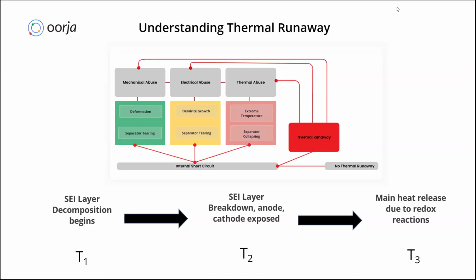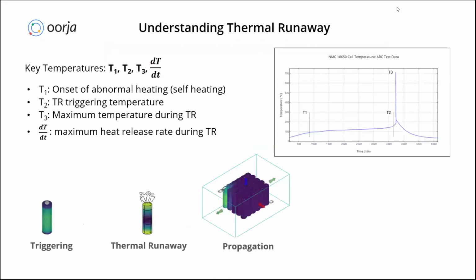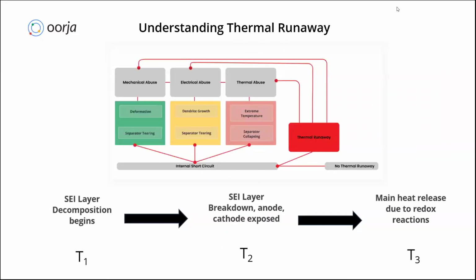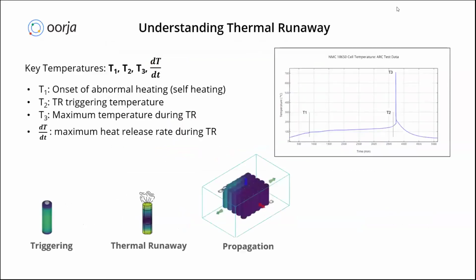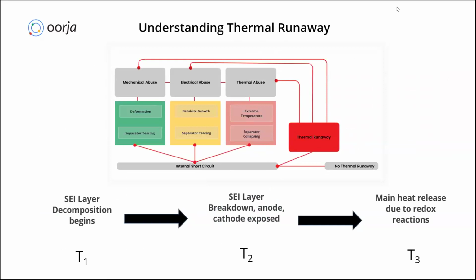So as I was mentioning, there are three characteristic temperatures present in any ARC signature or thermal runaway signature of the cell. At T1, the first temperature, which is the onset of abnormal heating, the SEI layer decomposition starts. Then at T2, the thermal runaway triggering temperature, the SEI layer breakdown happens and the electrodes, cathode and anode, get exposed. After that, at T3, the maximum temperature the cell reaches during thermal runaway, the main heat release due to the redox reaction happens, and that's when the cell reaches the maximum temperature during thermal runaway itself.